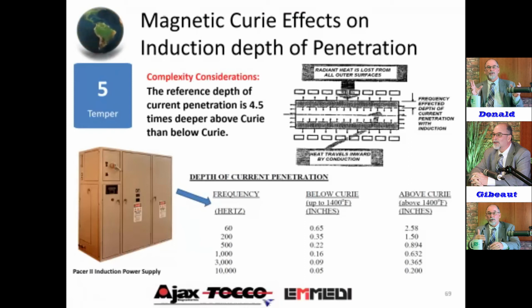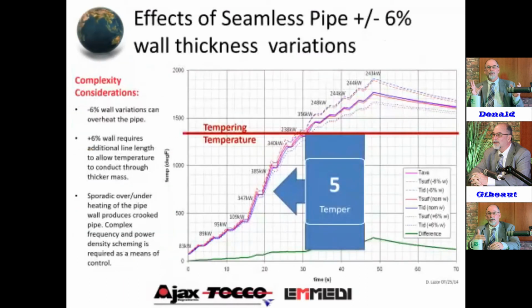When we produce those magnetic or the delta T curves, you can truly see the delta T collapse together a lot faster when you get above the magnetic Curie than below Curie. And that becomes a tool that we use in the upset frequency scheming, as well as in the seamless, where we talked about the wall thickness variation in the frequency scheming that we use there in the power density algorithm below the magnetic Curie. This depth of penetration is a critical element in the design of the line and its functionality.